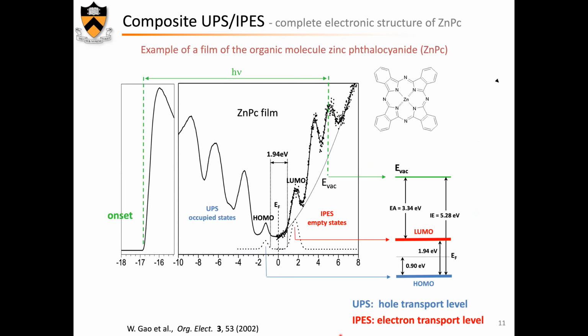Okay. So here is an example of a measurement that we did quite a few years ago on a film of this molecule, zinc phthalocyanine, where you can see on the left here the occupied molecular level, obtained by ultraviolet photoemission spectroscopy. So this is the highest occupied molecular orbital. And on the other side, the unoccupied molecular states with the lowest unoccupied molecular orbital. So out of all this, and other measurements that I will not go into in detail here, to measure the position of the vacuum level, you can get a pretty full picture of the electronic structure